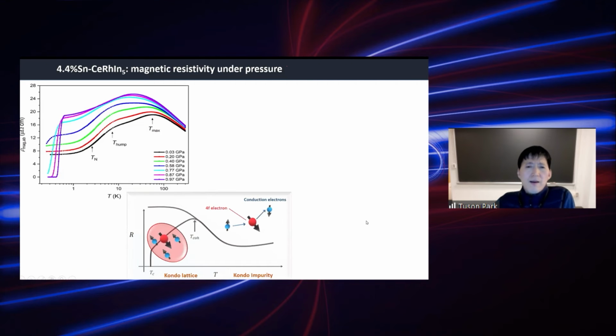Okay, so here we show the magnetic resistivity under pressure, in plane. At high temperature, the magnetic resistivity increases because of the Kondo scattering. And then there are three characteristic temperatures: around 50 Kelvin, the broad maximum, which we ascribe to the crystal field splitting; then the hump around 8 Kelvin, which we ascribe to the coherence of the doublet ground state; and the T-Néel around, I think, 2.7 Kelvin, 2.4 Kelvin.